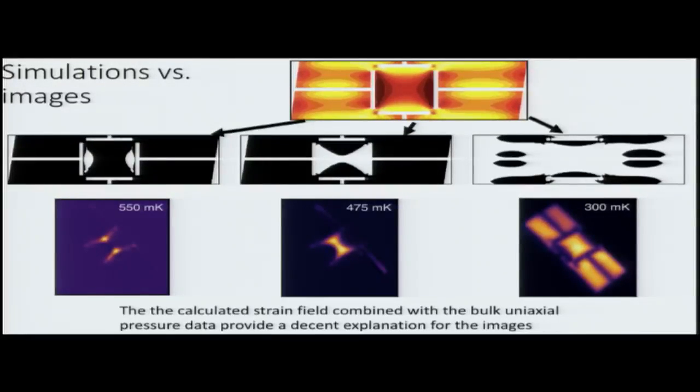And as long as that is not tens of microns thick, it does transmit the strain pretty efficiently. We have put a thin gold layer on top with the same boundary condition. That didn't seem to do much. But the glue layer seems to be like this at the bottom, and then in these structures there's also a little bit of glue touching the sample from the side, and I think that actually has a more significant effect.